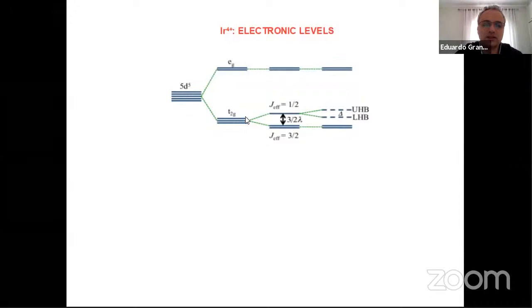And now, because we are talking about a heavy element, the next important interaction here is the spin-orbit coupling. Since we have 5 electrons, you may have up to 6 electrons in the t2g. We are most interested in this t2g level, and the spin-orbit coupling splits it into two different energies. The good quantum number here is the total angular momentum J_eff, which could be 3/2 or 1/2, because t2g has an effective orbital moment of L equal 1, and we have a spin of 1/2. This sum of angular momentum leads to two good quantum numbers, 3/2 or 1/2, and there is a splitting caused by the spin-orbit coupling.